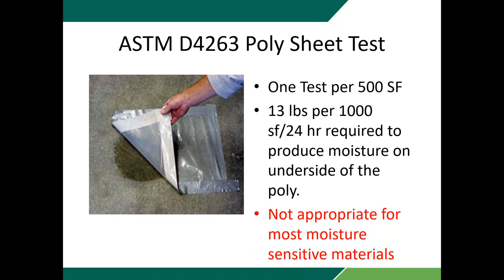Now, what a lot of people don't realize with this test is that in order for moisture to be present on the underside of that poly, you need 13 pounds per 1,000 square foot for 24 hours of moisture vapor drive. Now, I just told you that the typical limit is 3 pounds per 1,000 square foot. So running this test will certainly tell us if there's moisture present, but it's not a sensitive enough test to really be used with moisture sensitive flooring. And I still see it specified a lot, and I still see some manufacturers that call for it, even though their published limit is 3 pounds per 1,000 square foot. If you test with this test, you won't be able to determine if it's at 5 pounds or 6 pounds per 1,000. The only time you can make a determination is when the moisture drive exceeds 13 pounds per 1,000 square foot. So this test is really not suitable for moisture sensitive flooring like we're talking about today.